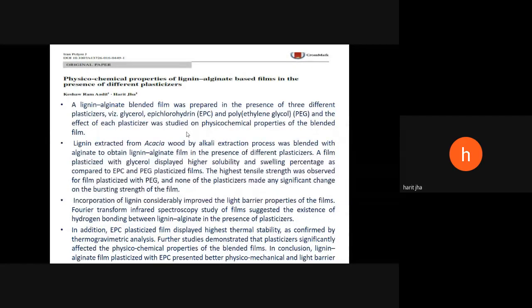The incorporation of the lignin considerably improved the light barrier properties of the film, and the Fourier transform infrared spectroscopy study of the film suggests the existence of hydrogen bonding between lignin and alginate in the presence of plasticizers. In addition, the epichlorohydrin plasticized film displayed higher thermal stability as confirmed by the thermogravimetric analysis.